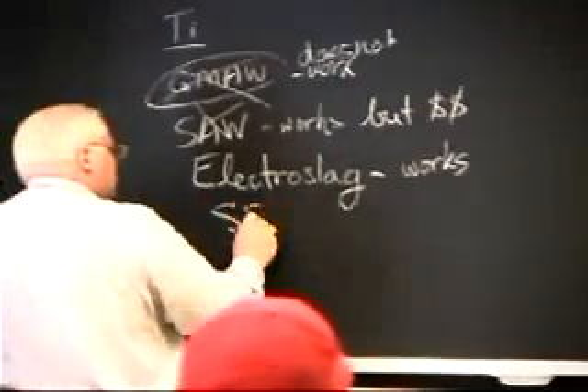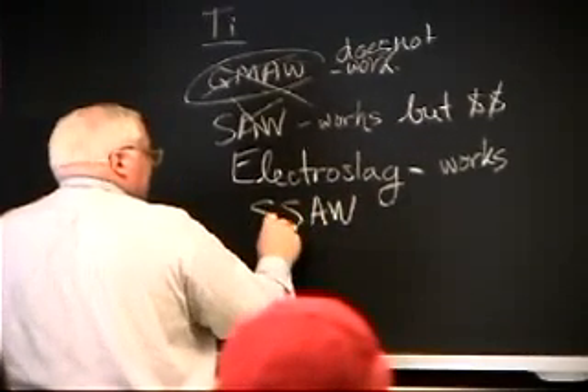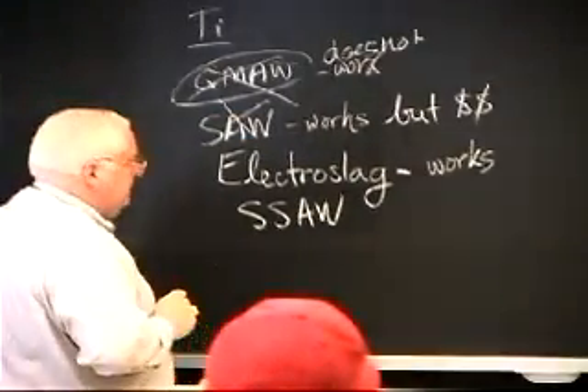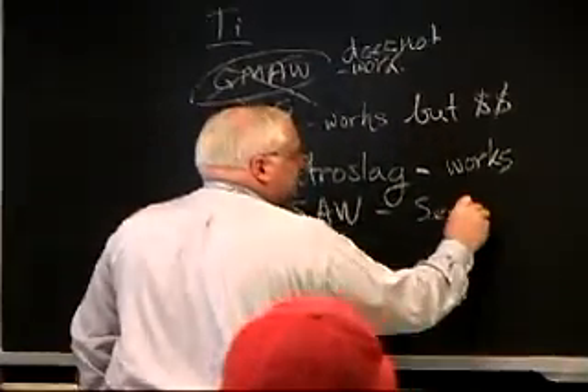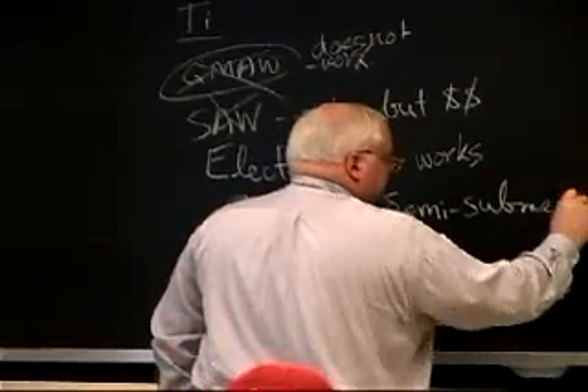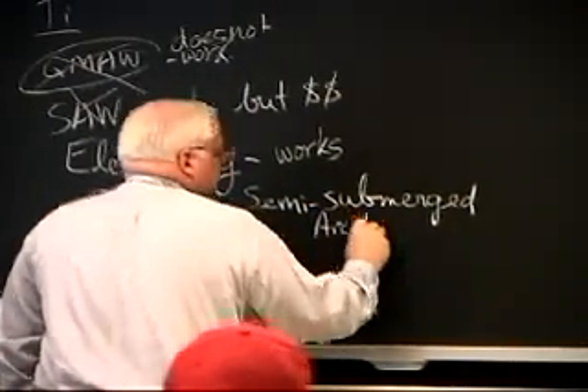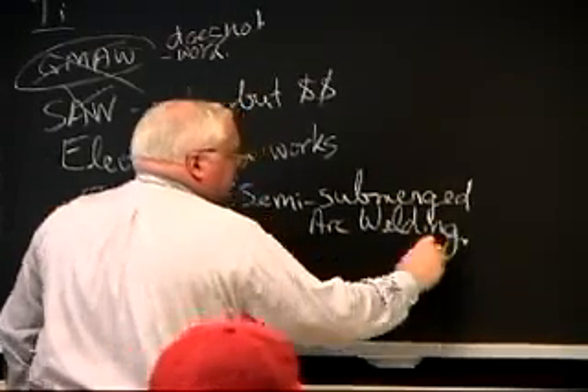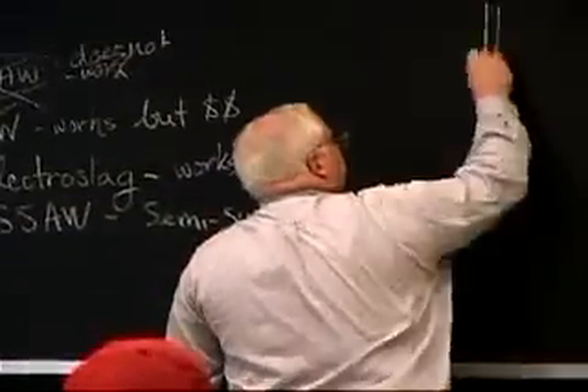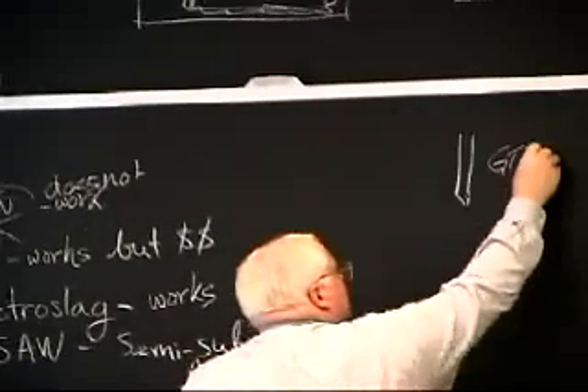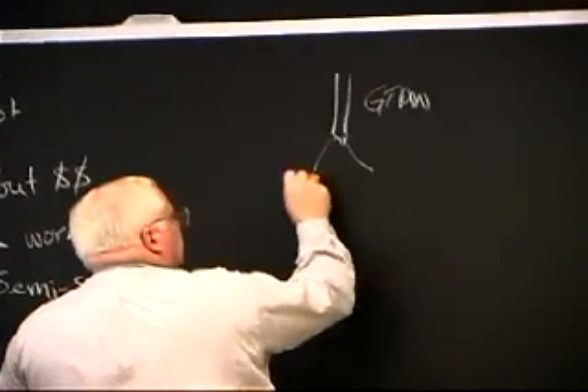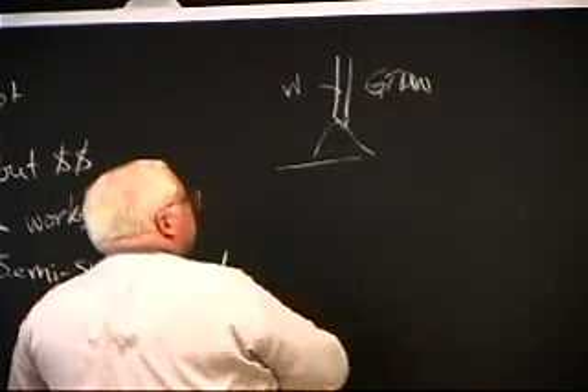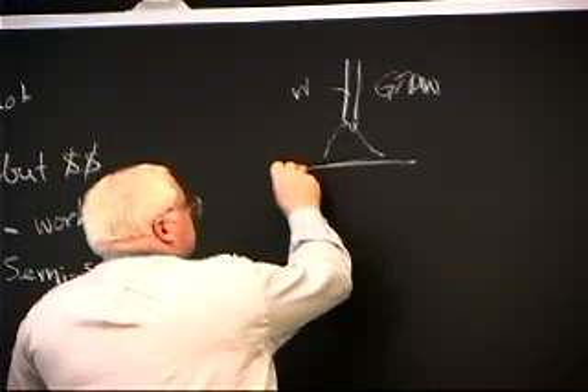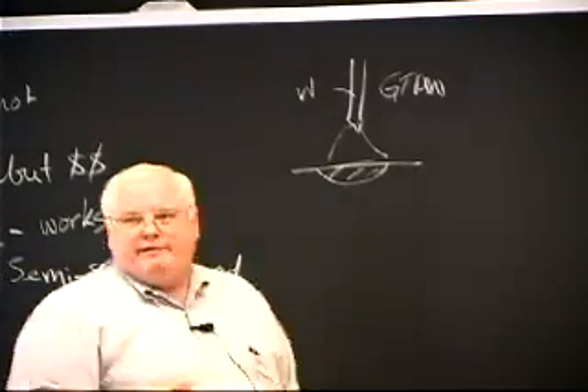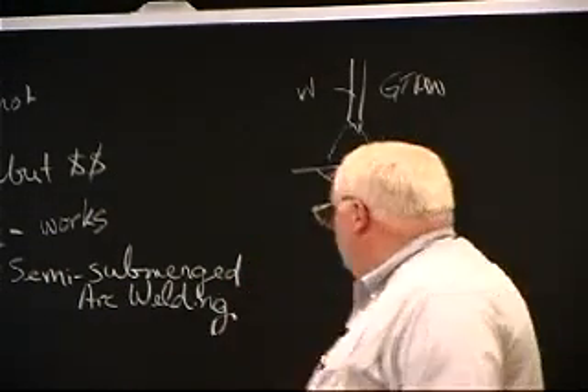So another thing is what the Soviets called Semi-Submerged Arc Welding. And it has nothing to do with this type of submerged arc welding. What happens is, if you're doing gas tungsten arc welding, which is a very slow process, you typically can't go above a couple of 100 amperes. So you have a tungsten electrode, W is the symbol for tungsten or Wolfram in German, and you weld this little bead here, and you're lucky if you get an 1/8 of an inch depth of penetration from that process.